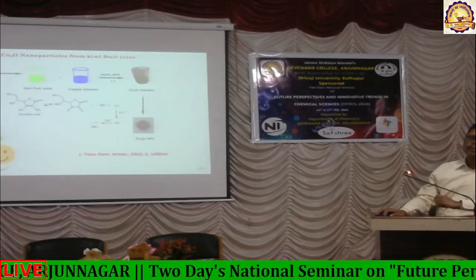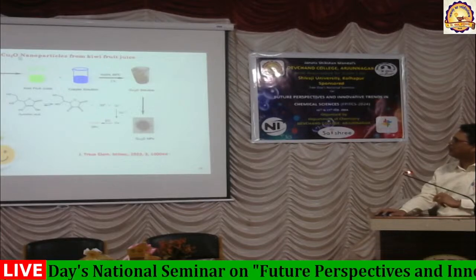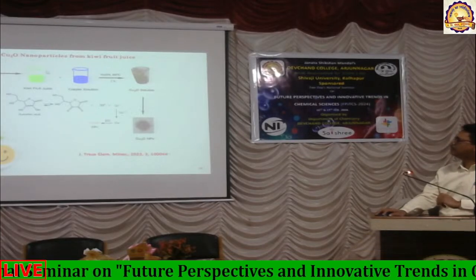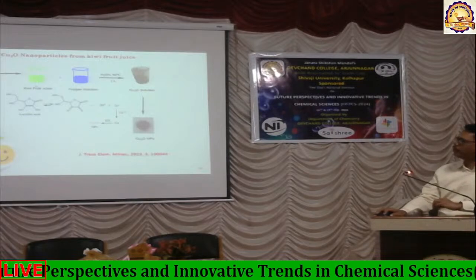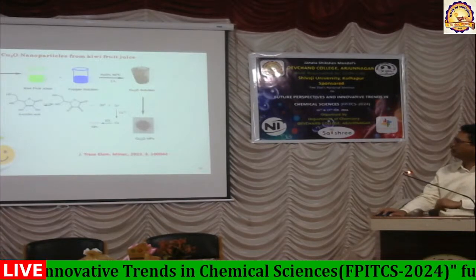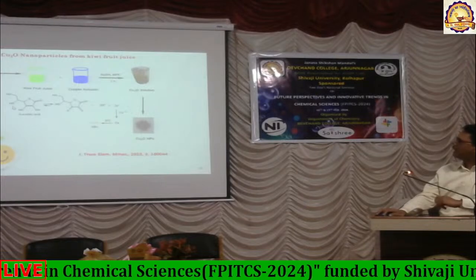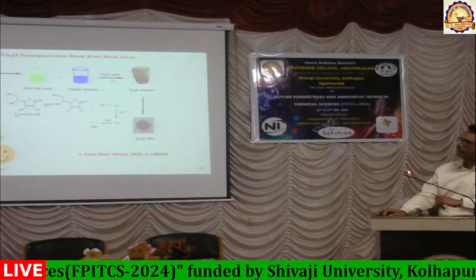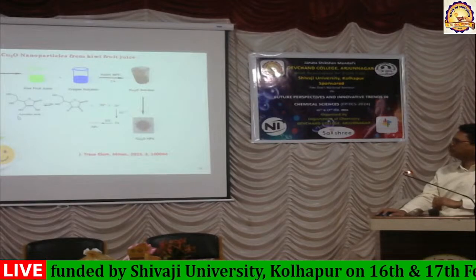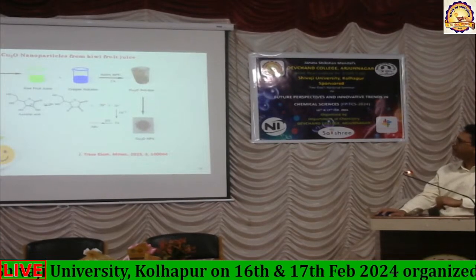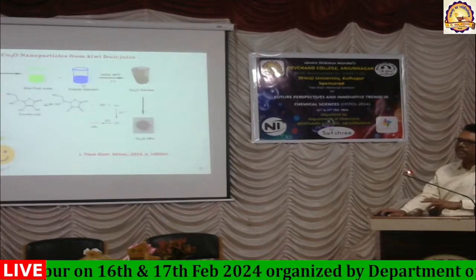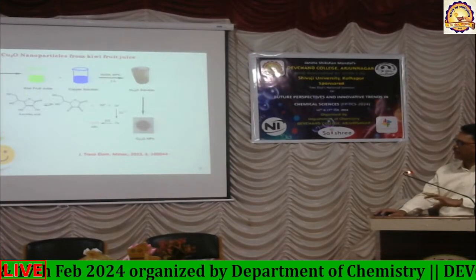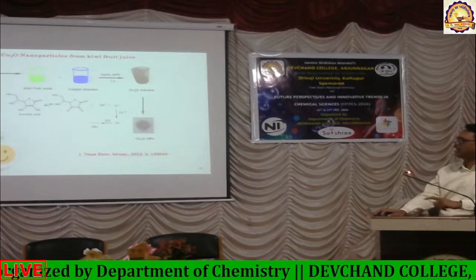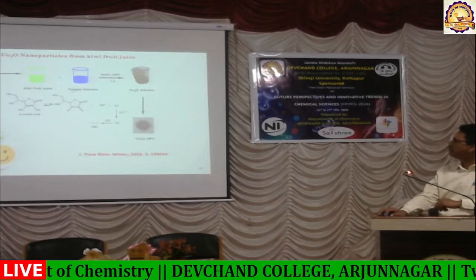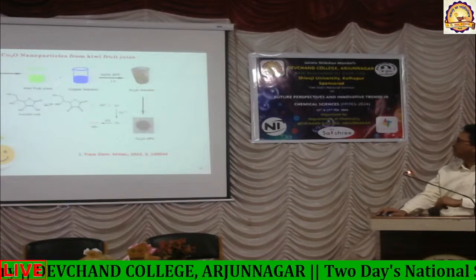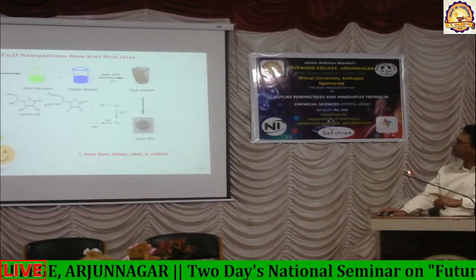Okay. So during COVID, many people were using kiwi fruit, which prompted us to make use of kiwi fruit, because kiwi fruit has got a lot of ascorbic acid. Around 5 to 6% of the juice contains ascorbic acid, which can reduce the copper very easily. Of course, copper, zinc, and silver can easily be reduced, and we got a copper oxide solution, which was converted into copper oxide nanoparticles by adding this simple kiwi fruit juice.